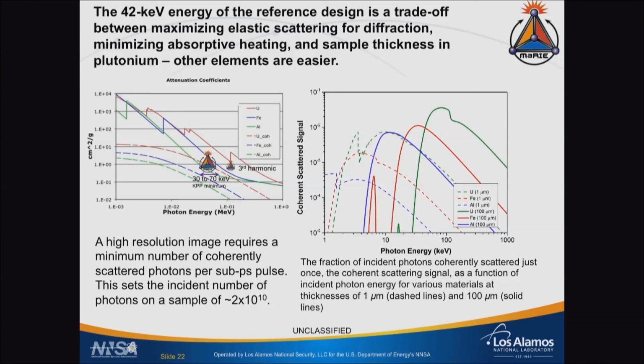If you're living down here at 8 keV, all these materials suck up a whole bunch of X-rays in one blast, and poof, they turn into a plasma. And so you want to be as far out this way as you can to be lowering the temperature. And this is decadal, orders of magnitude less absorption out here. This is the elastic cross-section, the cross-section for the good signal, for what will tell you about the scattering. And it does drop with energy, but not as fast. And you can see that the ratio basically is peaking in this many tens of keV range.